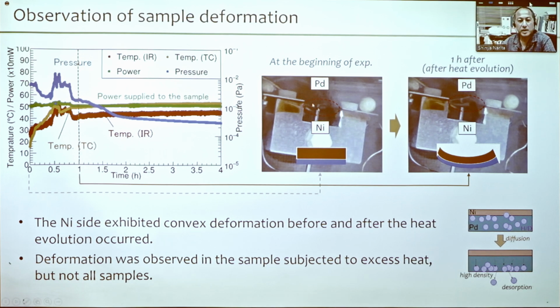So this is an image of the sample before and after heat evolution. It is hard to see the sample itself, so now I put some drawing here. Before and after the heat evolution, the nickel side exhibited convex deformation. But actually this deformation was observed in the samples subjected to the excess heat, but not all samples. So this result may be related to the hydrogen diffusion model discussed earlier, and it may also provide a hint for understanding how the exothermic heat evolution is induced.